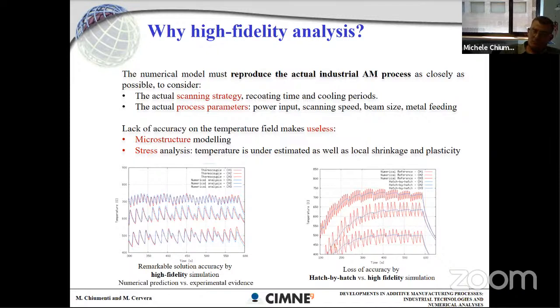Now, this worked very well when you go from fine mesh to coarse mesh. So when you are coarsening, it worked very well, and it retains the solution. Now, if you go back once again and you remelt, so you have to refine the mesh once again and then coarsen once again, this is much more tricky. And so we are still not able to do this cycling change of the mesh.